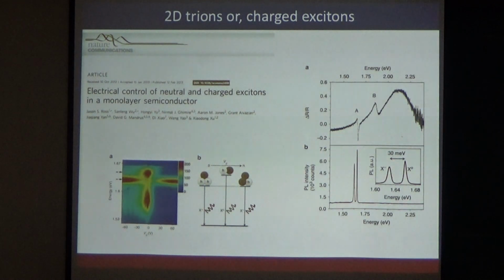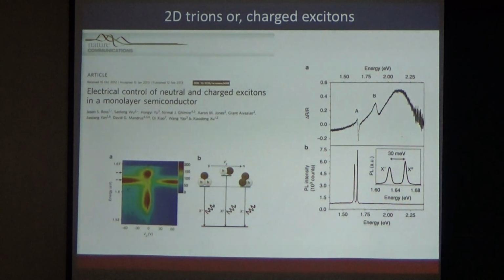So there we have two resonance peaks in this material, and by changing the electron concentration, if I now remove all the electrons, then we will only have excitons, right? And if I increase the electron concentration, more electrons will form bound states with excitons and they will become trions, which are charged excitons, right? So you can change from 100% trion to 100% exciton, and in between we'll have a mixture of trion and exciton. As a result, you can get an experimental curve like this, which is a two-dimensional color plot of intensity as a function of gate voltage and energy, where you can see that this is the neutral exciton at 0 gate voltage. As you tune the gate voltage in the positive and negative direction, you get another resonance curve, which is basically the negatively charged exciton and the positively charged exciton here, right?